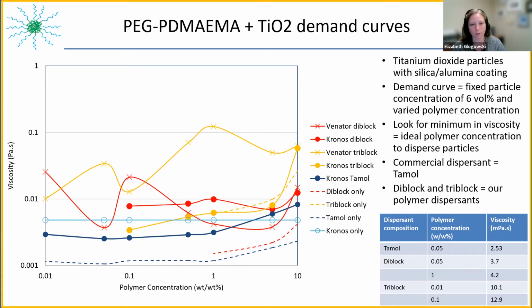And so we've done this initial testing, and with the graph with the log scale, it's a little bit difficult to read the actual values of the minimum. So I pulled those out into a table. And so what we see is that the values of the viscosity are the same order of magnitude for the minimum compared to our reference dispersant. And then the concentration needed to achieve that viscosity is in line with the commercially available dispersant.